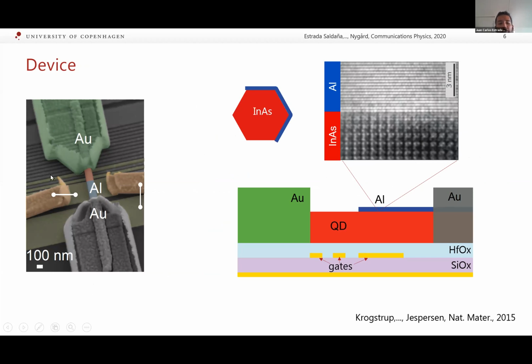And then by gating with these local gates underneath the nanowire and these side gates, and as you can see in the scheme, also this back gate below the whole device, we can define a quantum dot in the bare nanowire segment here in red.